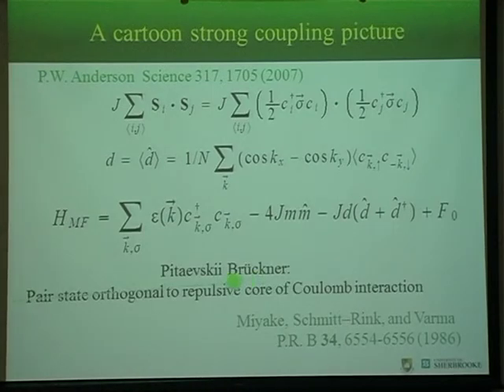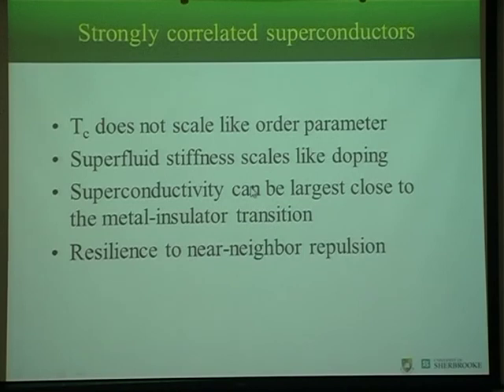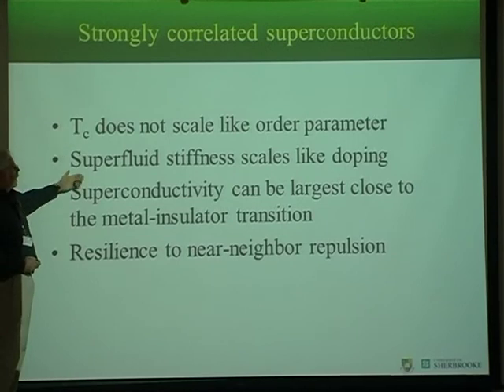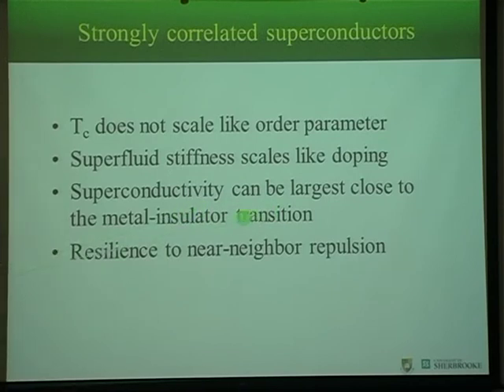This is credited by Anderson to Pitaevsky and Bruckner. In other words, the pair state is orthogonal to the repulsive core of the Coulomb interaction. That's why you get D-wave. So in the talk that I will give at the workshop, I will describe in particular what I call strongly correlated superconductors and show some differences between strongly correlated and weakly correlated. In the strongly correlated case, Tc does not scale like the order parameter. The superfluid stiffness scales like doping. Superconductivity can be largest close to the metal insulator transition. And there's a resilience to nearest neighbor repulsion.